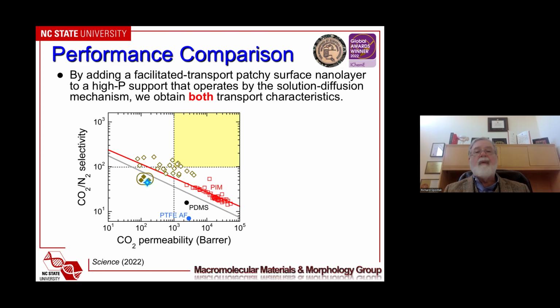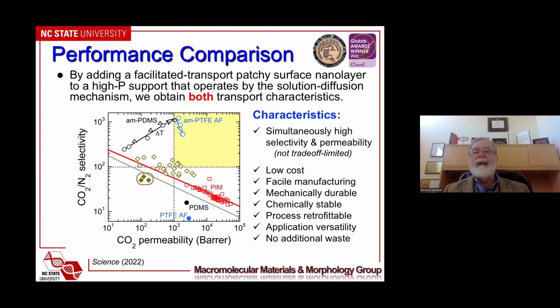If we want to look now at the materials that I've just shown you, this is where we are. So with PDMS, depending on the temperature, we can be down here, but if we increase the temperature, we can actually get into the Goldilocks regime. And for the aminated PTFE amorphous form, we're definitely high in this Goldilocks regime.